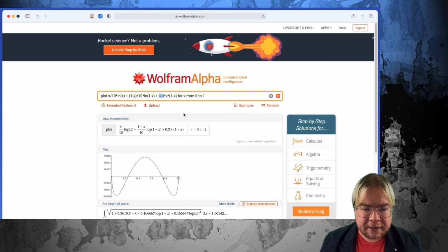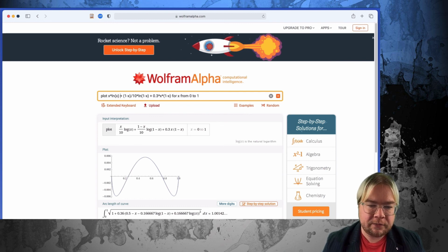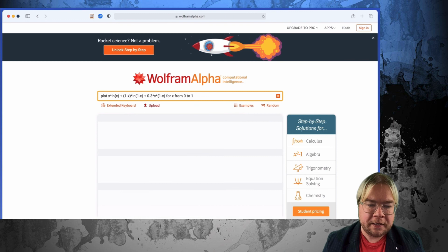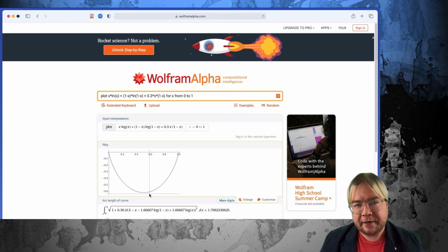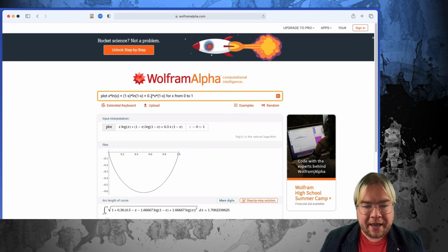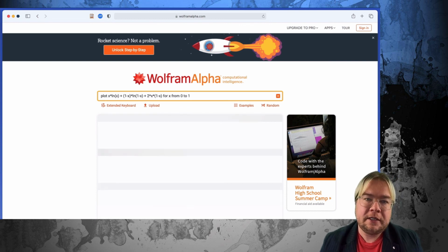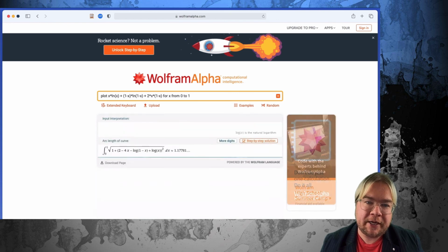Notice that a chi parameter of 0.3 is leading to this shape, which I said is causing instabilities in our system. Compare that to the case of the regular solution if I get rid of these degrees of polymerization. If I do that, then for the same interaction strength, I still have this U-shaped curve, which is going to be indicative of a system that mixes. And you can see that it's going to take much larger values of the chi parameter to get to a situation where I start to see demixing.